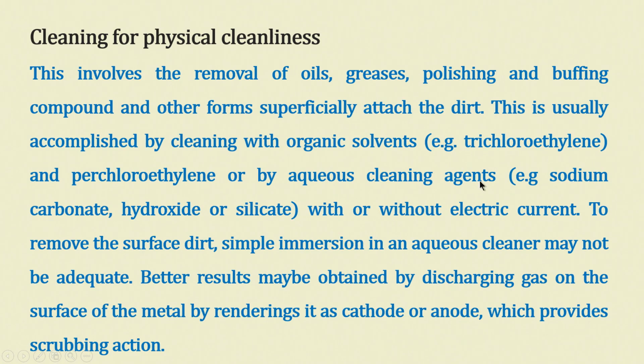Then it can also be cleaned with alkali, sodium carbonate, sodium hydroxide, sodium silicate, etc., as mixtures or as individual compounds also, with or without electric current, with or without heating also. I have not written heating here, but you should understand that higher temperature makes a difference in cleaning. That is why we wash the clothes also in warm water to see that the dirt is blown away. So, the sodium hydroxide, sodium carbonate, sodium silicate are used individually or in mixtures.